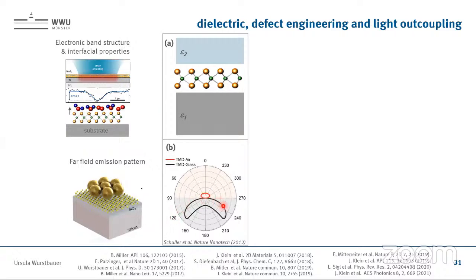We can effectively adjust the far field, the light outcoupling properties. So what is plotted here, you see a 2D material on a glass substrate, and that's the far field emission pattern to the air interface, and that's to the glass interface. It's the same emitter, so the intrinsic properties are really the same. It's just how much light you can guide out. And you can imagine if you have a high aperture optics here, you can couple much more light to the glass side than to the air side. And also here we have the tunability because it's extremely thin.